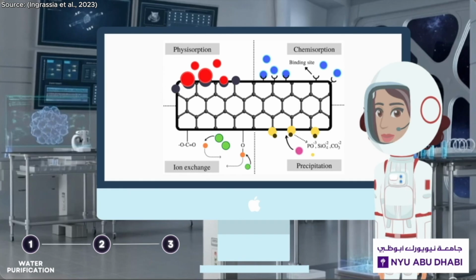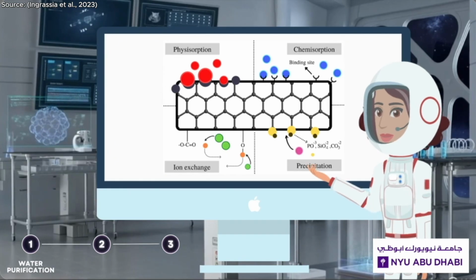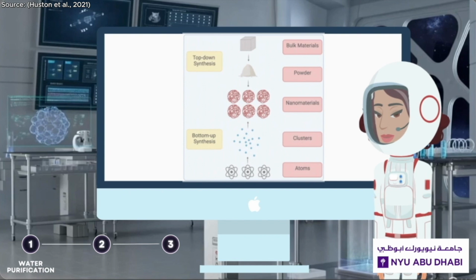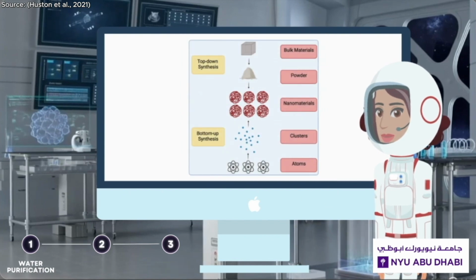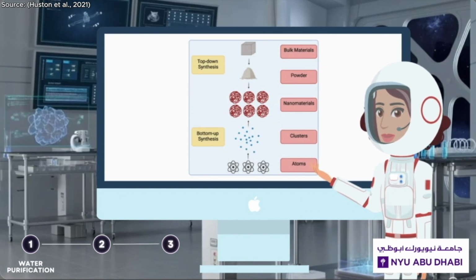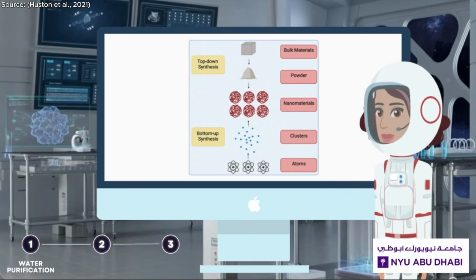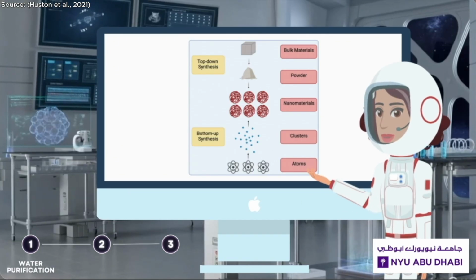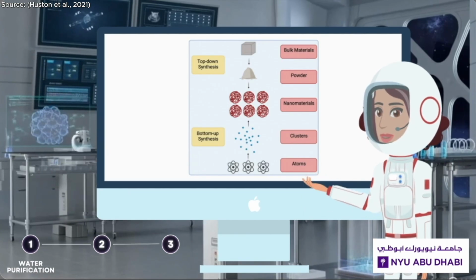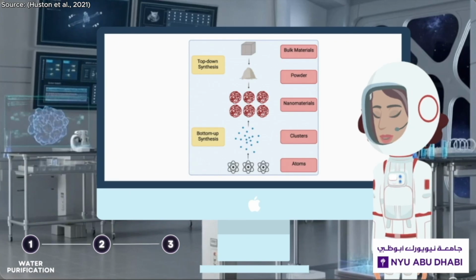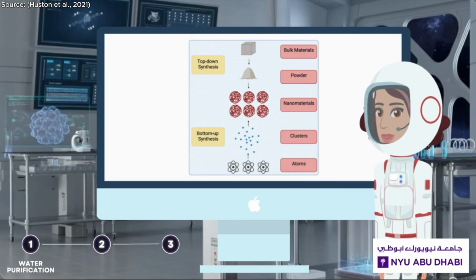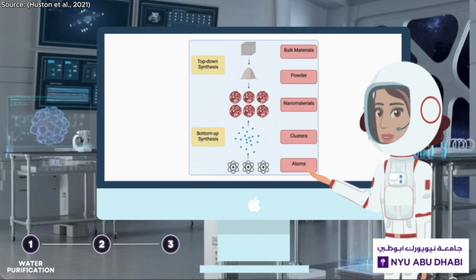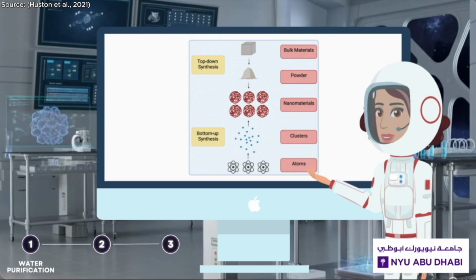Magnetic nanoparticles are especially useful as they allow easy regeneration and recycling through a magnetic field. The synthesis method determines particle morphology and surface functionality, both of which influence efficiency. The top-down approach breaks bulk material into nanoparticles via milling, lithography, or laser ablation, which can produce inconsistent adsorption sites. In contrast, bottom-up synthesis, through chemical vapor deposition, sol-gel processing, or biological routes such as plant extracts, enables precise control over particle structure and surface chemistry, yielding more uniform and efficient adsorption.